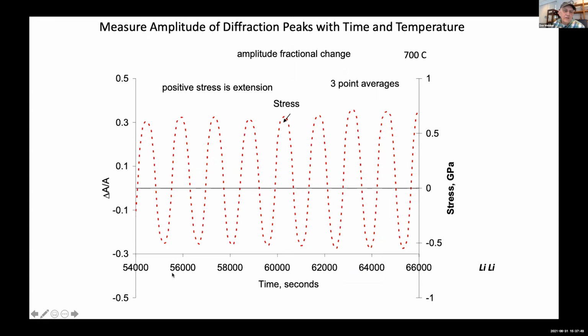Now, here's an example where we moved into the plastic region by going to higher amplitudes. This is 2,000 seconds between these tick marks. And so this tells you that the period of this wave is a little less than 2,000 seconds. And this is the stress that we measured, as indicated over here in GPa. So it's going plus or minus half a GPa.